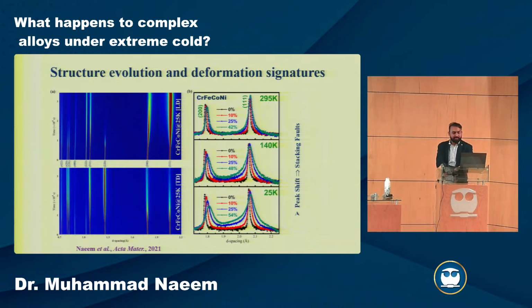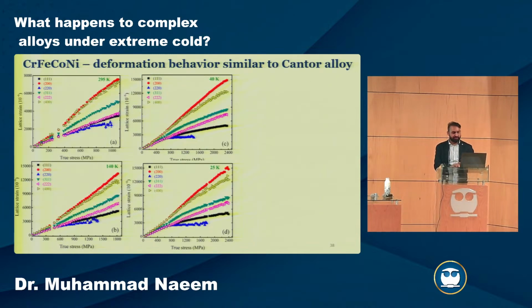And this is very simplistic, what I'm going to say, but you have to make things simple in order to really deconvolute. So the relative peak shift is usually associated with stacking faults. Then the peak broadening, that's basically the signature of dislocation density increasing. And if you have this asymmetrical broadening, that's related to twin faults. And then we can quantify these by using certain models or equations.